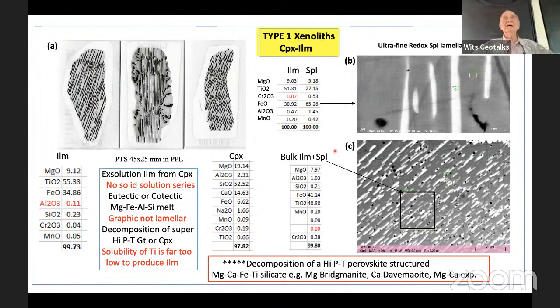Now, the reverse is absolutely super abundant, namely titanium magnetite with ilmenite lamellae. Randall and others thought earlier on, Buddington, for example, all thought that was an exsolution process. Nay. You cannot, once again, remove it. The only way to do it is to reduce it. It was the famous Don Lindsley, fortunate enough one of my mentors, who demonstrated that in order to produce this intergrowth, it had to be oxidized. Now, the reverse applies here. We have a spinel in the ilmenite rather than an ilmenite plus the spinel. And the only way to produce this then is by subsolidus reduction rather than oxidation.